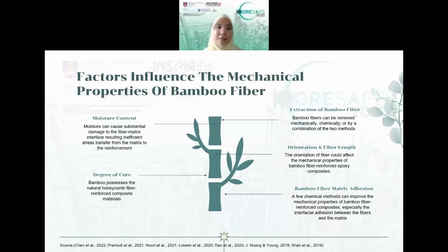So there are several factors that influence the mechanical properties of bamboo fibers, such as moisture content, which we know can cause damage to the fiber matrix interface, resulting in inefficient stress transfer from the matrix to the reinforcement. Degree of cure, where bamboo possesses a natural honeycomb fiber reinforced composite structure. Extraction of bamboo fiber, where bamboo fiber can be removed mechanically, chemically, or by a combination of the two methods. Orientation and fiber length, where the orientation of fiber could affect the mechanical properties. And bamboo fiber matrix adhesion, where there are a few methods that can improve the mechanical property of bamboo fiber reinforced composites, especially the interface between the fiber and the matrix.